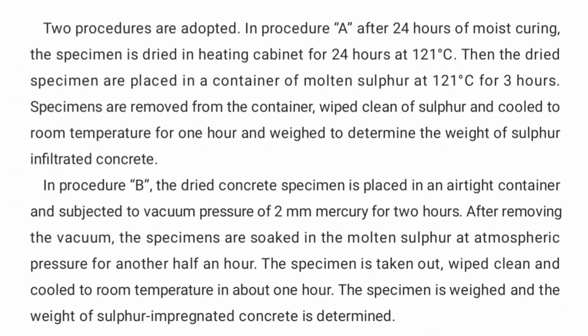So, two procedures are adopted. First, in procedure A, after 24 hours of moist curing, the specimen is dried in a heating cabinet for 24 hours at 121 degrees Celsius. Then the dried specimens are placed in a container of molten sulphur at 121 degrees Celsius for 3 hours. The specimens are removed from the container, wiped clean of sulphur, cooled to room temperature for 1 hour, and weighed to determine the weight of sulphur infiltrated concrete.